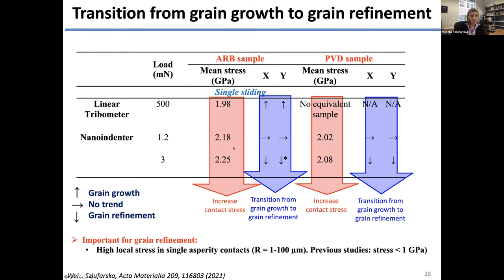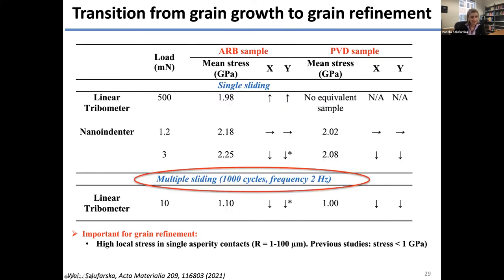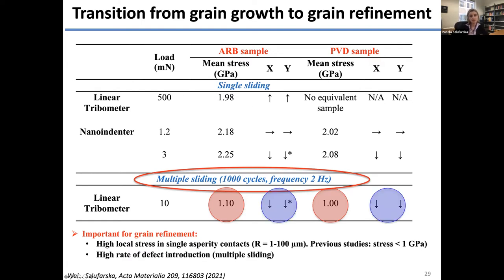Now, it turns out that when we performed another experiment where we had multiple sliding, this is using the tribometer, it was 1,000 cycles, the stresses in this case were lower, about 1 gigapascal. So we would expect from the previous experiments that it would be grain growth in this case. However, we still saw grain refinement. So what it means is that even at lower stresses, it is possible to induce grain refinement during wear of these nanocrystalline ultrafine grain aluminum if the deformation occurs at high enough rate and defects are introduced fast enough. So what do I mean by that? Let me just show you the mechanisms that we found.